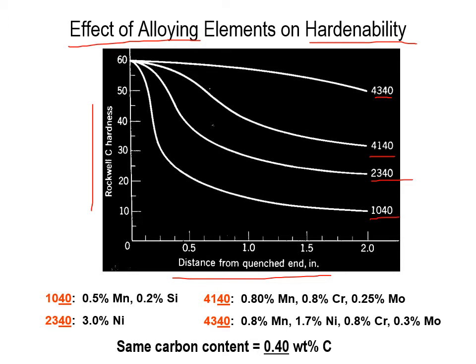We can see as we start off here, right at the end, I have a hardness on the Rockwell C scale of 60, and you can see the 1040 drops off in hardness much quicker, almost down to about within the first half inch here before it starts leveling out. Whereas the other one, if you take a look at the other end of the spectrum, is 4340. It stays level and is more of a mellow change as you get further away from the quenched end.